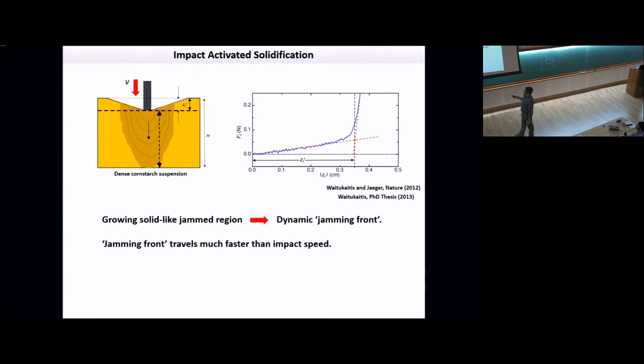Once that happens, since this point of impact is connected to the solid boundary by a solid-like material, it is really difficult to compress it further. If you study the force response on this rod as a function of displacement, initially in this growth phase, the force on this rod increases very slowly. But once this solid region extends to the container boundary, then force shoots up by orders of magnitude.